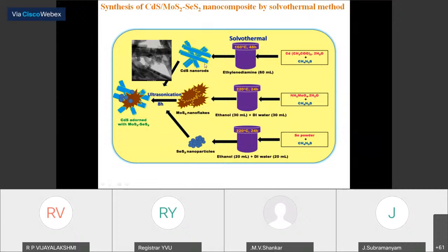So what we did in our laboratory is we prepared the nano composite. To prepare the composite, the process we adopted here is ultrasonification. So we have the cadmium sulfide rods. Then after ultrasonification with molybdenum sulfide and selenium sulfide, we obtain the composite. That composite is nothing but the cadmium sulfide, molybdenum sulfide, selenium sulfide nano composite. So like this, we synthesize the nano composite in our laboratory.